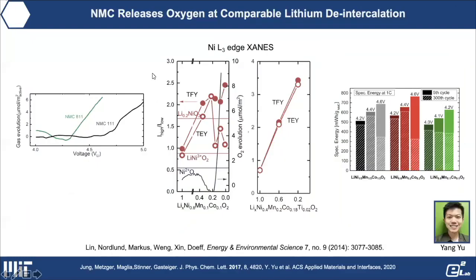Through the work of Hubert Gasteiger in Munich, they have shown that NMC 811 has a much earlier voltage onset for oxygen evolution relative to other lower-nickel NMC materials. As we and others have shown recently through X-ray absorption spectroscopy, NMC 811 essentially oxidizes or releases oxygen at a comparable oxidation state of nickel — or comparable lithium de-intercalation amounts — relative to other nickel-based materials. This raises a really interesting question.